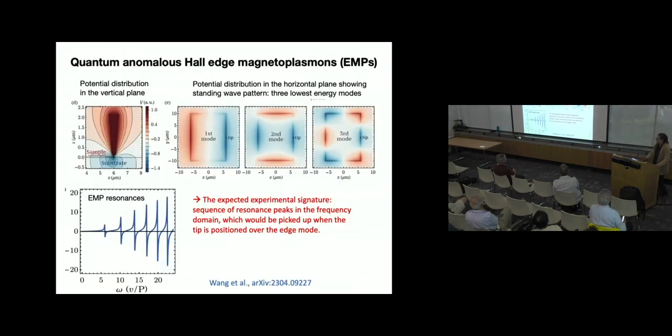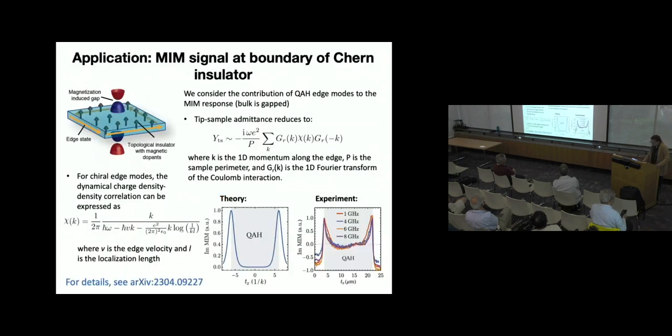So also, just to return to the question that was asked earlier, we were talking about quantum Hall data earlier, but normally we think of the edge state of a quantum Hall system to be determined by the magnetic length, which is usually tens of nanometers. We're observing something much more broad in our data, and that's because the relevant length scale that characterizes the width of these edge states is determined by the momentum of the edge magnetoplasmons.